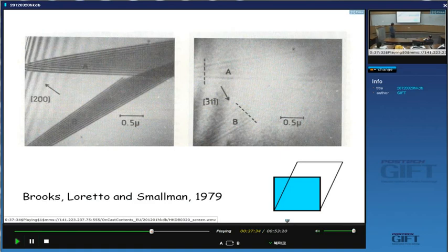Okay? A stacking fault is like a thin layer of epsilon martensite. But you have to prove that, because it can only be epsilon martensite if there's also a volume change. Right? And this experiment proved that individual stacking faults also have a volume change.